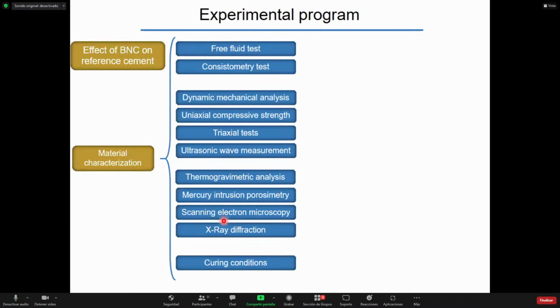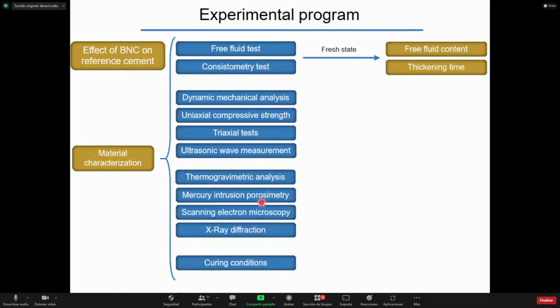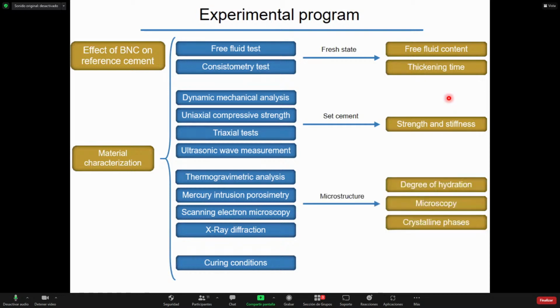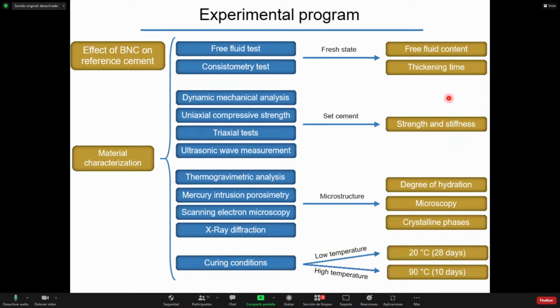Now, in order to determine the effect of bacterial nanocellulose on cement, we had to characterize this material. So we performed a free fluid test and a consistometry test on the fresh state to determine the free fluid content and thickening time. We performed dynamic mechanical analysis, uniaxial compressive strength, triaxial test, and ultrasonic wave measurements on set cement to determine the strength and stiffness of the material. We performed thermogravimetry analysis, mercury intrusion porosimetry, scanning electron microscopy, and X-ray diffraction on the microstructure to determine the hydration and the crystalline phases. All of this was done on 2 different curing conditions: low temperature at 20 degrees for 28 days, and high temperature of 90 degrees over 10 days.